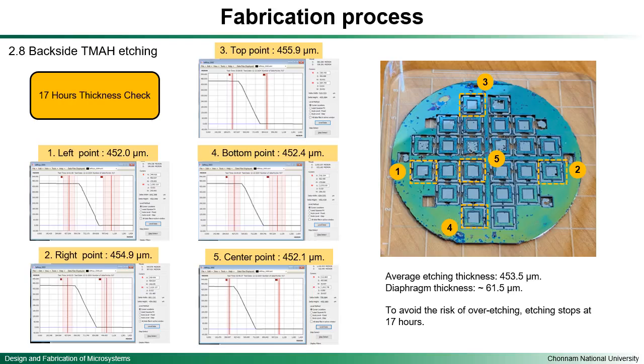But finally, we did our etching for over 17 hours. When we reached 17 hours, we tested the thickness again. This time I tested the 5-point thickness of the diaphragm. The 5-point average thickness is around 453.5 micron. Based on the base thickness of the wafers, the diaphragm thickness is around 61.5. To avoid the risk of over etching, we stopped here. So our diaphragm thickness is around 61 micron.